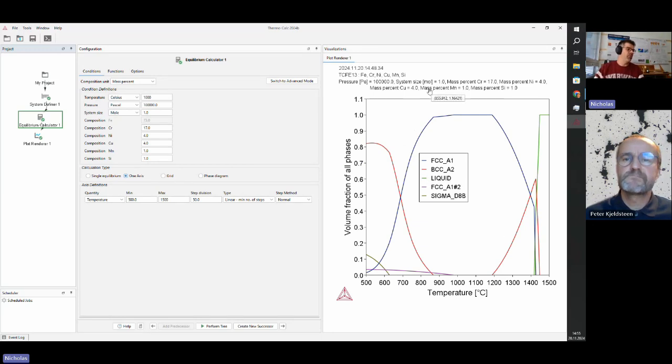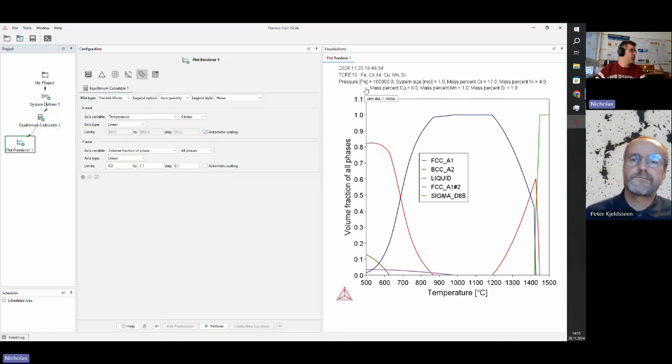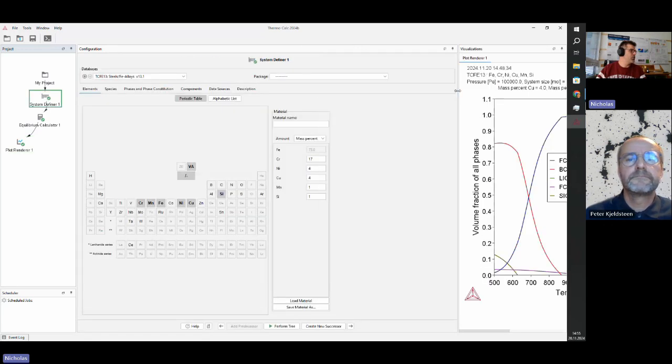So we've got the phases, right? At 400, it's mostly BCC. If we cool this reasonably slowly, the austenite will probably decompose and it will be ferritic, so BCC, right? So it's obviously precipitating copper out of BCC. And then the first thing that I have to do if I want to do a nucleation and